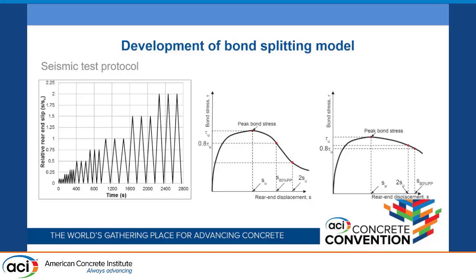And again, we said this has to be different from what we do for anchors, because in the case of anchors, the loading protocol is mainly for non-structural applications where we have a constant crack, or crack cycling is there, but then we have load cycling within a particular range, typically 75% or 50% of the peak load. And we said, no, we want to understand the full behavior throughout the range of interest. So that means not just what happens in the initial loading cycles, but also throughout its load-displacement behavior.